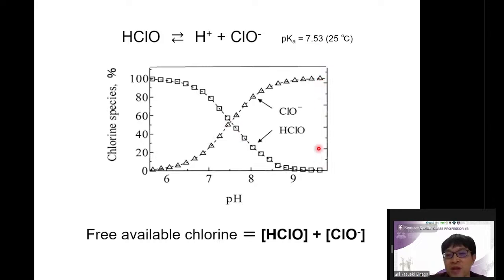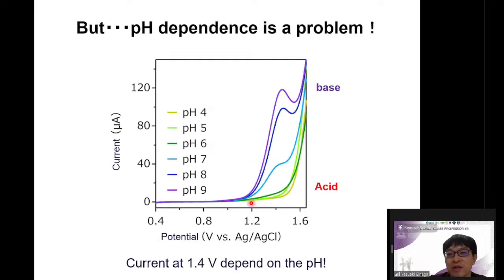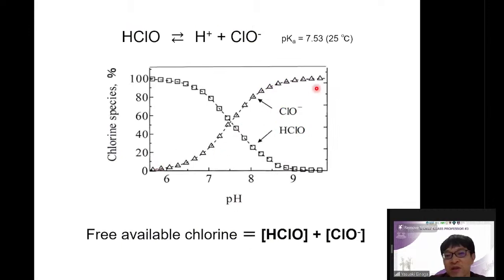So when the pH is high, ClO minus is almost 100%. On the other hand, when the pH is low, HClO is dominant. So this is obvious. Our result shows the oxidation of ClO minus. So it means this is reasonable, of course. When ClO minus is much, of course the signal is high. When ClO minus is low, the signal is low. This is reasonable. However, for the practical sensor, we need to know the concentration of free chlorine, meaning both HClO plus ClO minus. So this is not enough. Only this one is not enough.